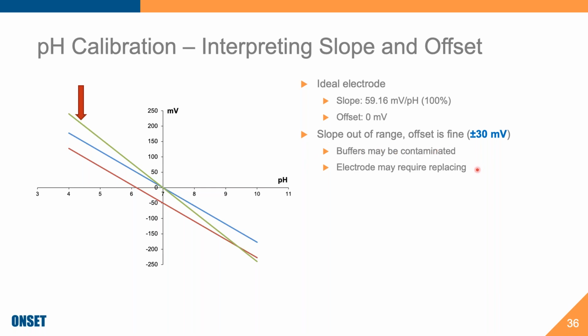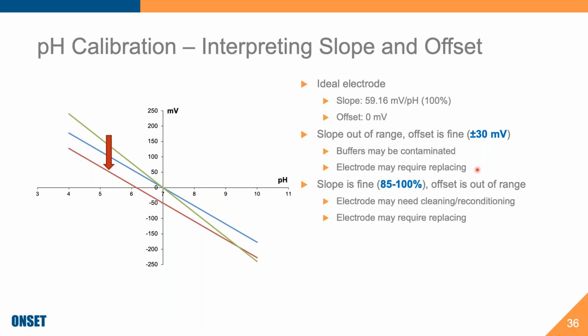My recommendation whenever you have either a slope or an offset that are off, the first step should always be for you to do a visual inspection of the electrode to make sure there are no cracks, as well as to look to see if your electrode needs cleaning, and go ahead and try cleaning it and then reconditioning it before trying your calibration again, because that might just be the problem. And I'll talk about that in a little bit.